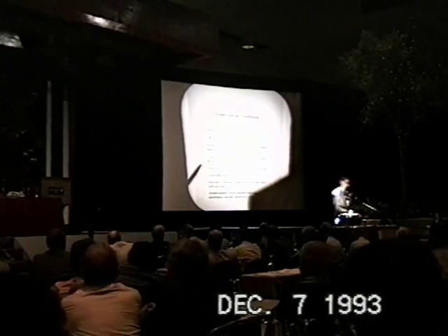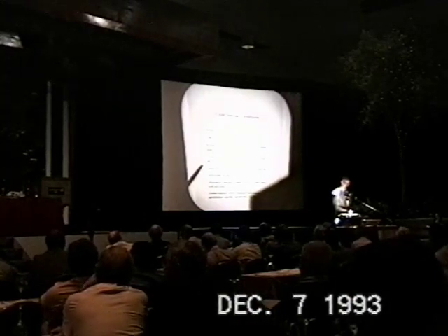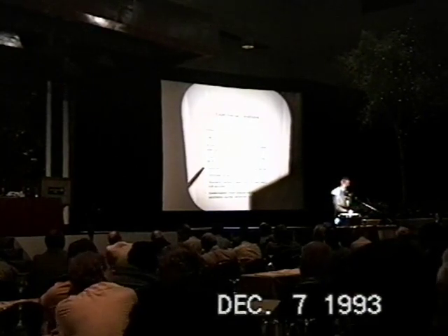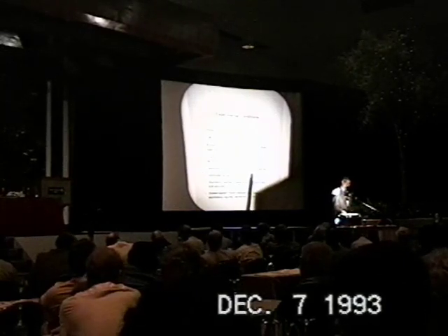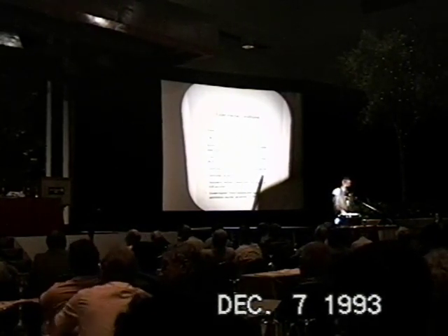We did perform other experiments not reported here today on 4N9 pure material produced by Johnson Matthey, and also in some cases by a third manufacturer. We were using controlled current electrolysis at quite low current densities, namely only between 5 and 20 milliamps per square centimeter. We had our reasons for that.